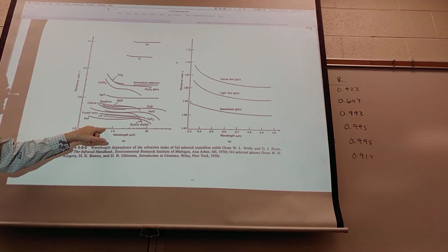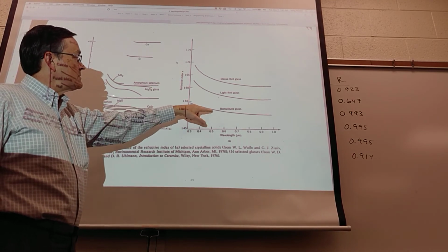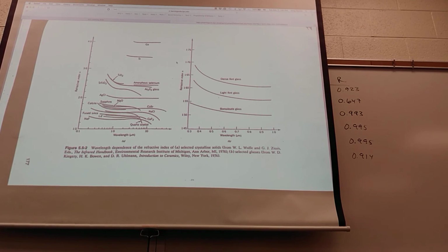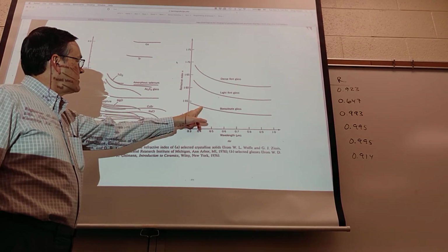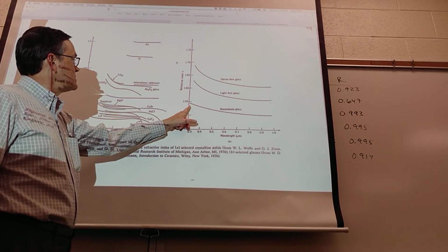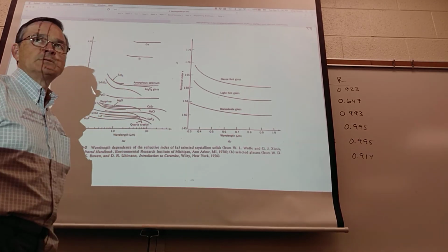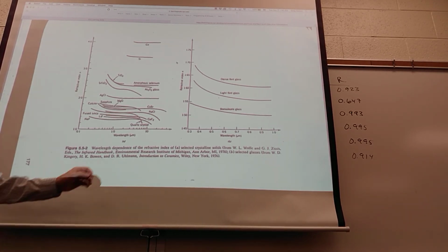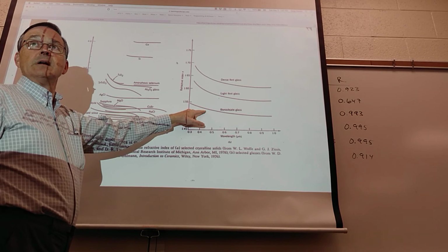If we take a look right here, expanded on a linear scale, refractive index for several different types of glasses. Borosilicate glass, that's just the everyday glass you see everywhere: windows, microscope slides, etc. You can see at 0.4, which is where our eyes cut out on the short wavelength end of the spectrum, it is about 1.53-ish. Over here, 0.7, it's about 1.52-ish. So over the spectrum that we can see, refractive index is decreasing. Basically, that's the dispersion of borosilicate glass.